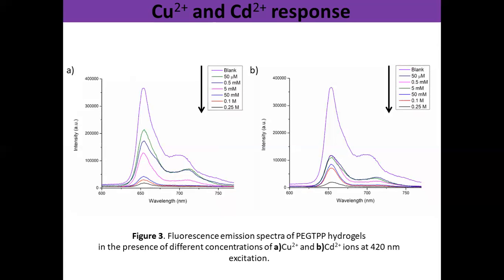The addition of a little copper 2+ and cadmium 2+ leads to significant quenching of the fluorescence emission from PEG-TPP hydrogels. For the 0.25 molar ion solutions, a 99.5% decline in intensity at 655 nanometers is observed, demonstrating the high detection capacity of the hydrogel.